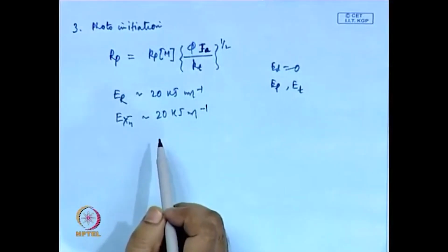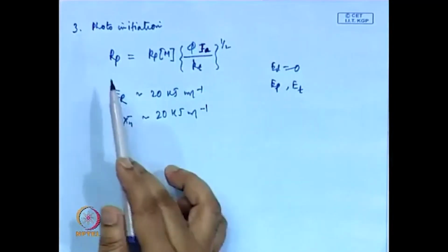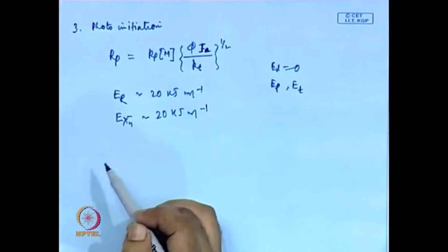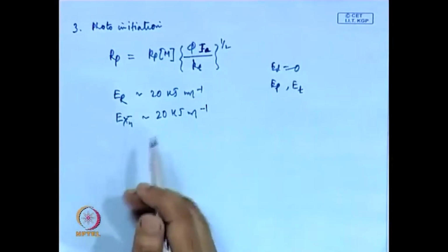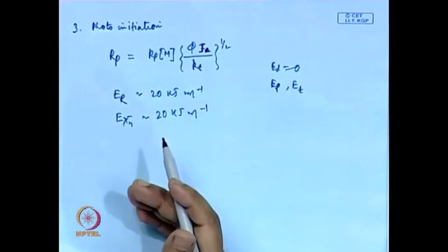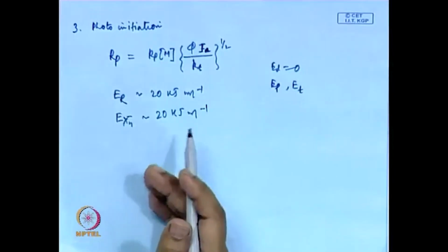However, you should remember that the temperature effect in a photochemical reaction is a little more complicated, because the initiators which produce radicals photochemically also produce radicals at a higher temperature. So if you increase the temperature, there will be complications about which type of initiation is dominating, and this equation will be a combination of a photochemical reaction and a thermal initiation.